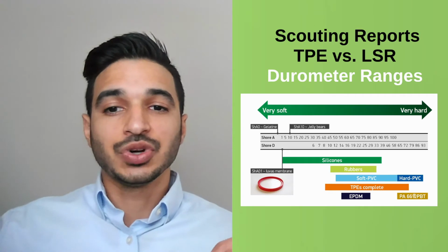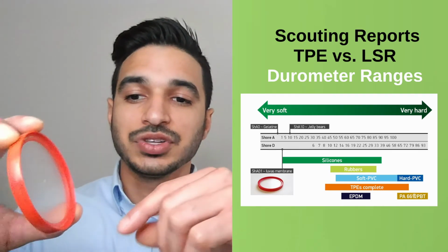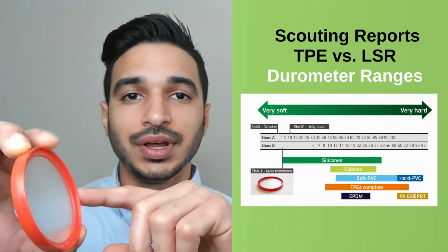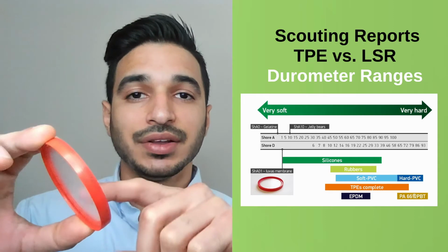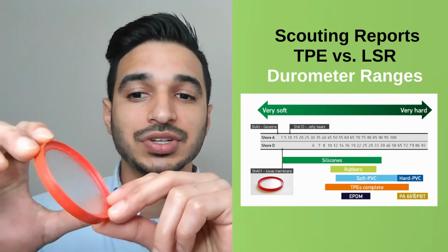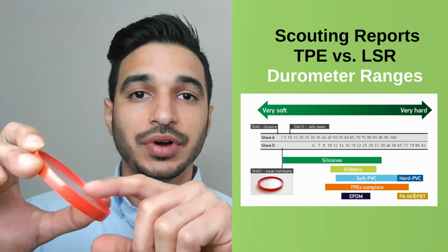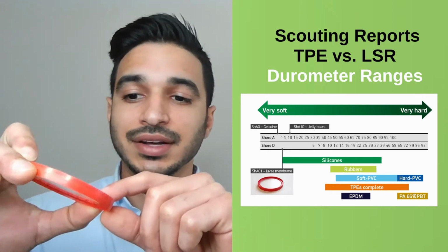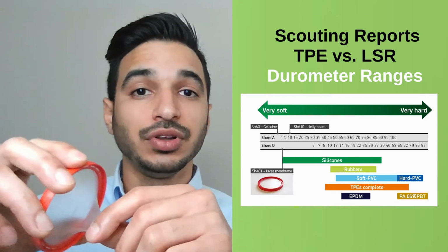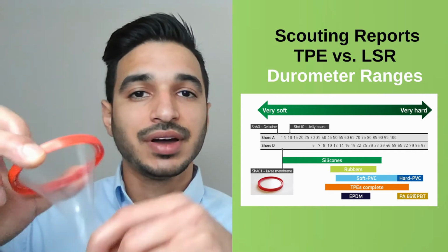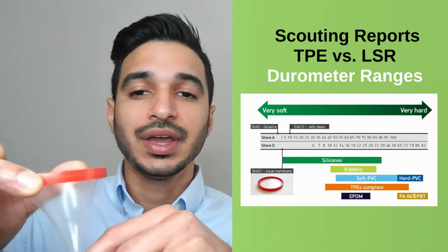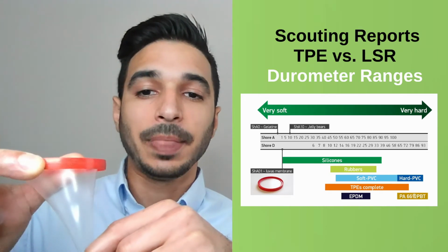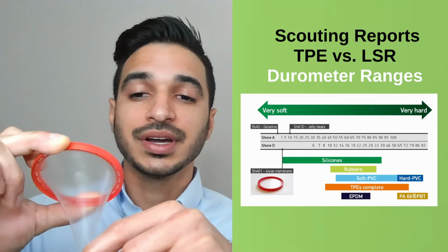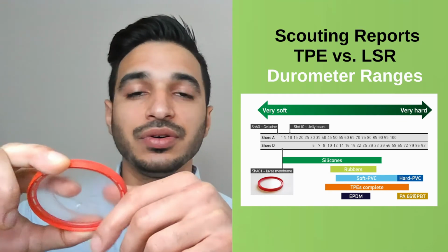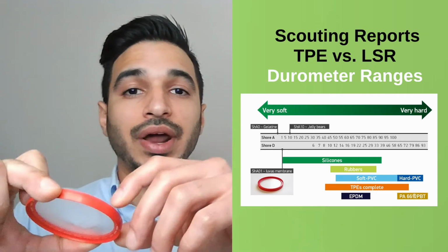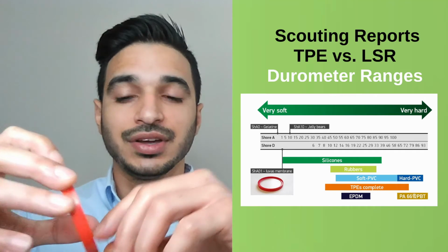Here I have an example to show you the extreme flexibility of LSR on the lower side. This is a two-shot component combining PBT and a self-adhesive LSR that is rated for food-grade applications. The thickness of this membrane is 0.1 millimeters. And this component acts as a balloon. So it's filled with liquids and fit inside of a cup used for the elderly community. Since you don't have to tilt the cup back too much in order for it to compress and push the liquid out, this makes it ideal so there's not too much stress on your neck or any other joints as you're trying to drink your favorite beverage.